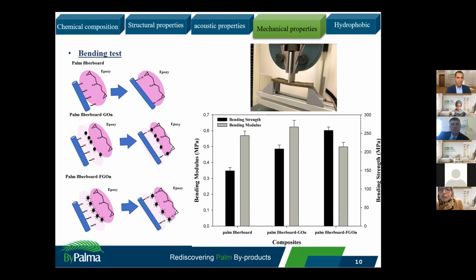And then the incorporation of modified graphene oxide showed a slight decrease in the bending modulus because of the rubber character of the long chain grafted on the graphene oxide surface. However, this modification plays a great role in enhancing the interaction between the matrix via enhancing the chain entanglement, leading to facilitating the strain transfer between matrix, fiber and graphene particles.